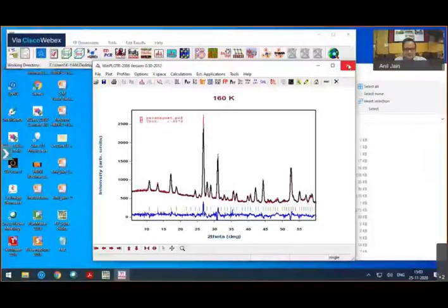Now the idea is, suppose you do not want to go ahead with this symmetry analysis, or you want to remove the restrictions associated with the magnetic structure which come from the symmetry analysis. Then, if your magnetic structure is commensurate, we can try to work with this simulated annealing mode and see if we can get information about the magnetic structure after removing the constraints from the symmetry analysis.